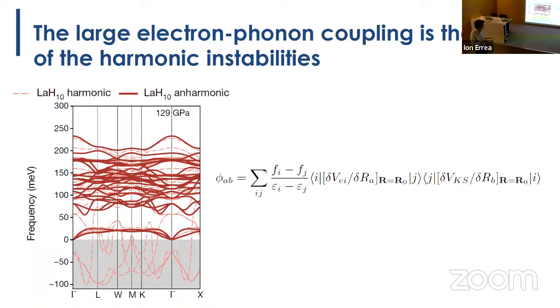So this is the harmonic phonons, and you can see here what we have. These are the harmonic dynamical matrices, if you want. These are Kohn-Sham states, i and j, and what we have here are the electron-phonon matrix elements, basically. So if the electron-phonon matrix elements are very large, and this contribution to the dynamical matrix is negative definite, the phonons will be lower. So somehow this is a message.